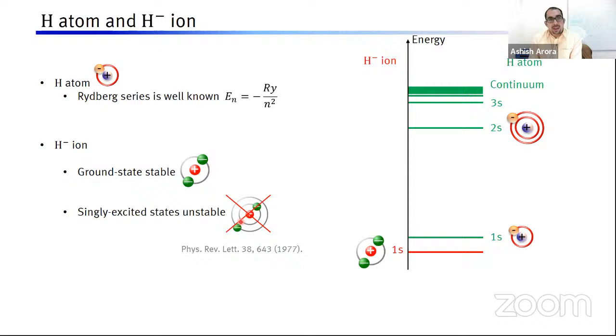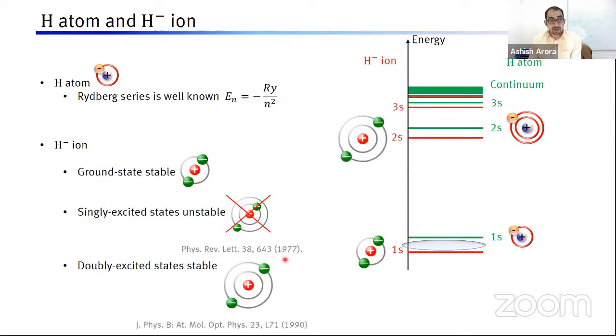However, if we add another electron in the 2s shell of the hydrogen atom, such an H negative ion is unstable. So such an H negative ion, which should appear somewhere here, is unstable. So it does not appear. Both theoretically and experimentally it has been seen. However, if you add both electrons in the 2s shell, such an H negative excited state is stable and it appears just below the 2s state.